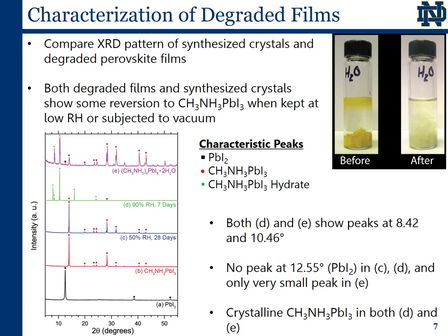This reversion can be seen in a change back to the dark black brown of the crystalline perovskite and in the appearance of peaks attributable to methylammonium lead iodide in the XRD patterns. And this reversion provides strong evidence for the formation of a hydrate of methylammonium lead iodide.